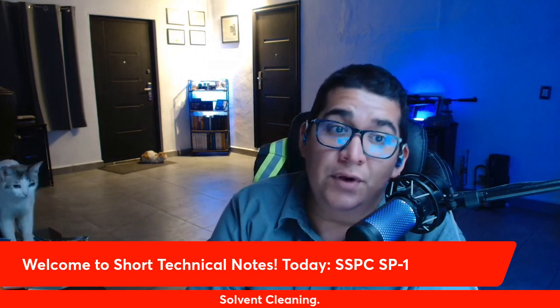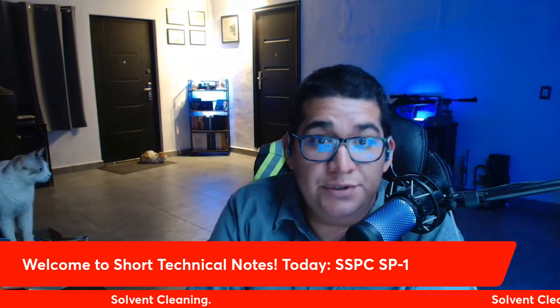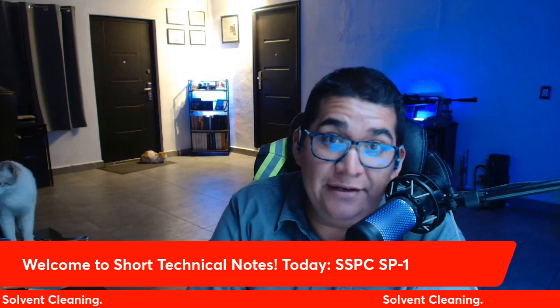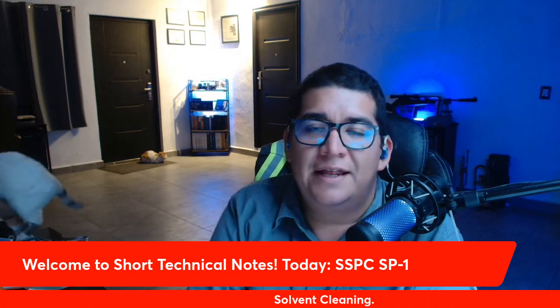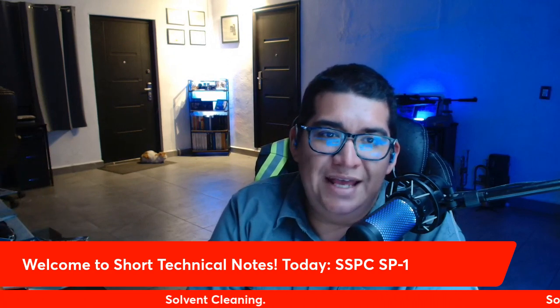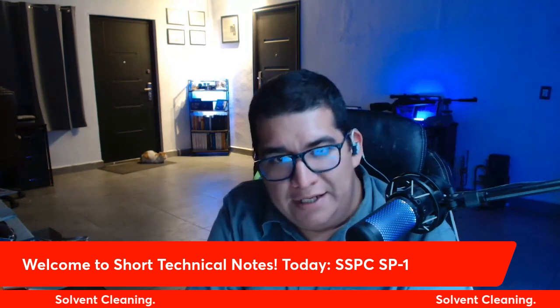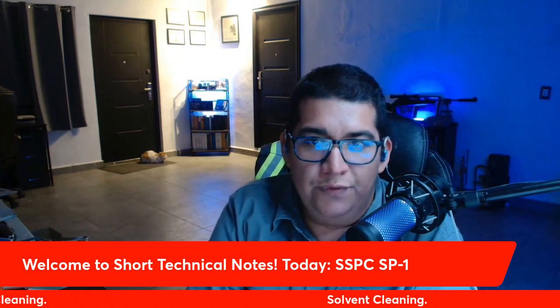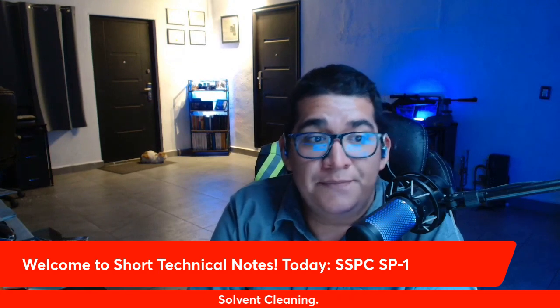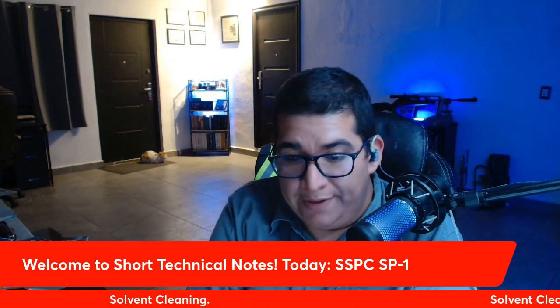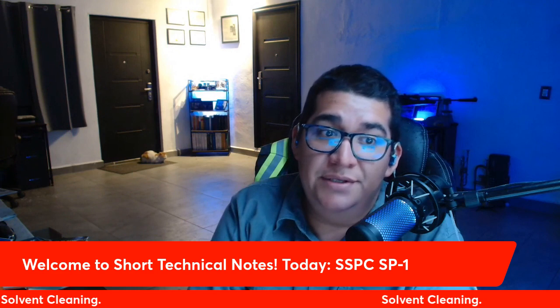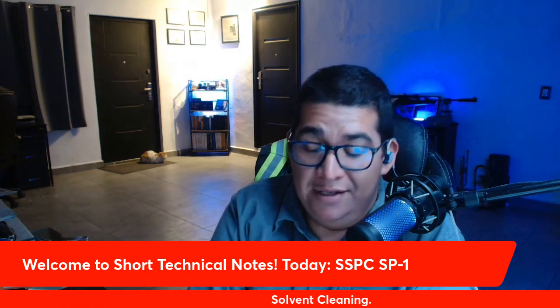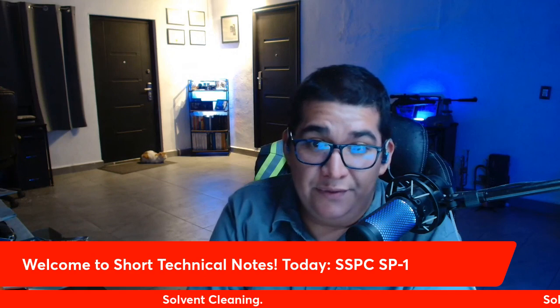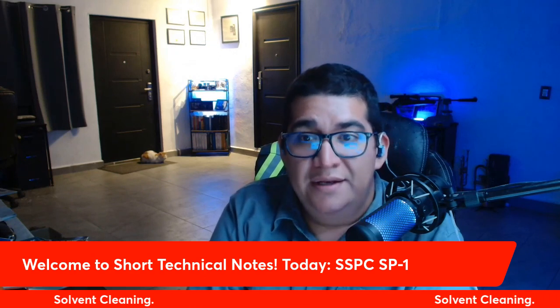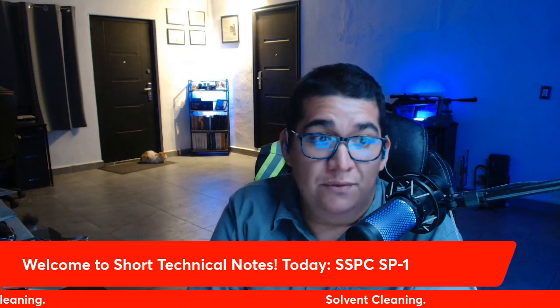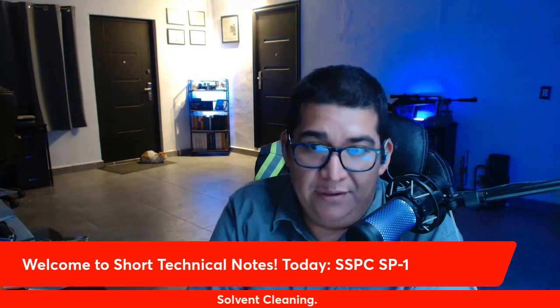The fourth requires the use of emulsion or alkaline cleaners. But there is an important fact: we need to use a washing step after this kind of cleaning in order to remove residual contaminants. What else? The last point mentions steam cleaning using detergents or cleaners, and then a water rinse or wash again. It is important, wash again.